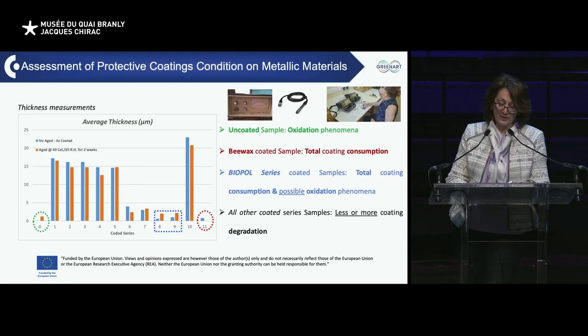However, one should monitor thickness alteration because the coating may disappear and an oxidation film on the metallic surface may develop. For example, specimen 0, which you see on the right, the uncoated metallic sample, presents an increase of its thickness due to oxidation after 2 weeks of artificial aging. On the other hand, the beeswax coated sample presents total coating consumption, and finally, some coatings under development, the Biopol series, present an increase, and this fact may be an indication of oxidation phenomena, locally or entirely, and needs, of course, further examination.